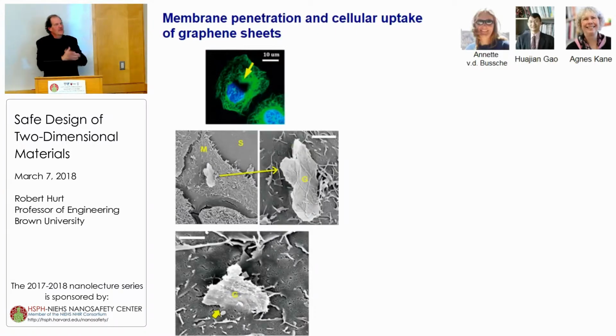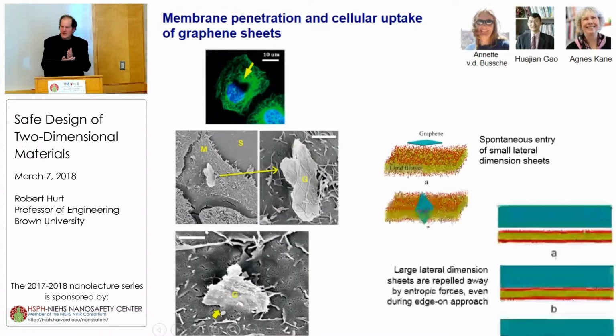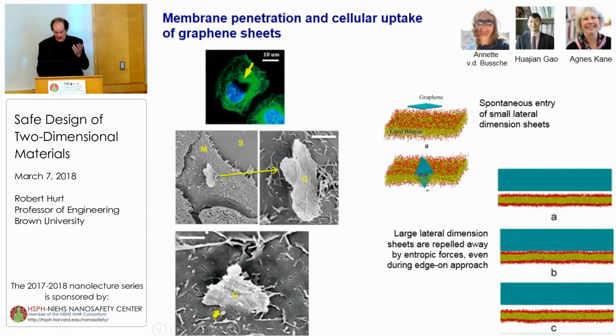And the first one comes from a few years ago, where Agnes in her lab and Annette van den Bossche, who was doing many of the experiments, found that these multi-layer graphene flakes that you can buy commercially are taken up by cells, and they're found in the near nuclear space, as you see here, often lying flat. And if you interrupt the process using ex situ SEM, you can see the process of entry as it's occurring. Instead of seeing invagination at these points, where the flake is being taken up by endocytosis or phagocytosis, it doesn't look like that. It looks like a more uniform cutting, even where the membrane may be extending outward. And this is a sign for passive entry or cutting of a material rather than active uptake, at least in the early stages.